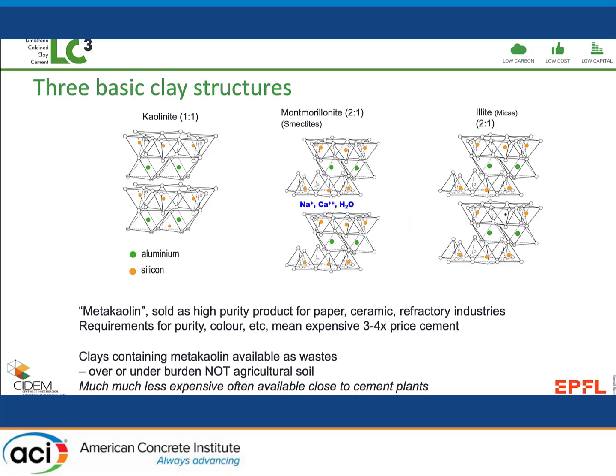And this is because kaolins are what's called one-to-one clays. They have a layer of silica and a layer of alumina, which means both the silica and the alumina can participate in the reaction. And this brings about lots of benefits, as was shown in earlier presentations, as in the one from Oregon State and the one by Mike Thomas.